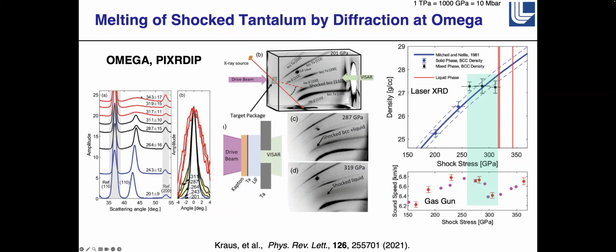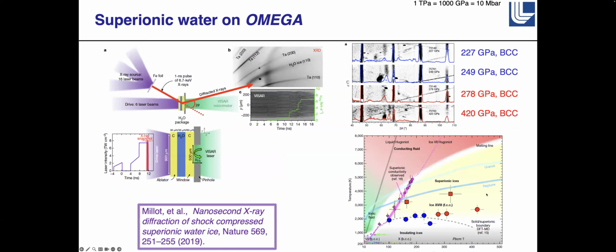And this is the diffraction of the 110 of BCC tantalum, and it shifts up with pressure, and then it gets very weak and it gets broad. This kind of shows that peak translated, so you can see that at about 264 GPa, you start to broaden this solid line, and these three images in black are shown as these three in black here, where the density doesn't change very much, and you see that the intensity drops and you start to broaden it. And so we interpreted that as the melting transition, which corresponds great to what was measured in gas guns. So that was exciting.